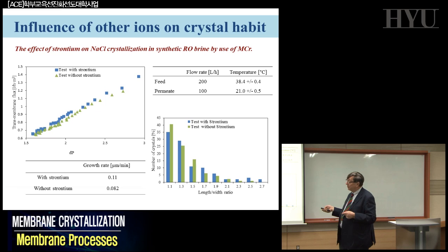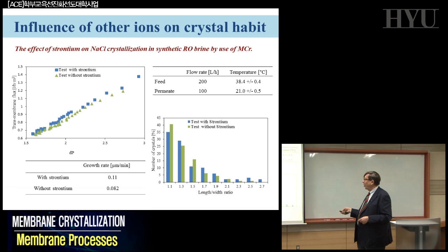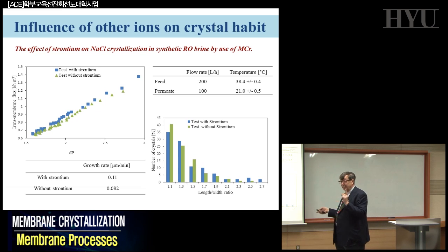But in our case, it's becoming a problem, because there is a different behavior in terms of the transmembrane flux when you have strontium present or you don't have strontium. And it's not huge, but it is present. More than this, you have some effect on the quality of your crystals. We are talking about making crystallization in a very well-controlled environment with very nice final products. However, if you have some strontium present, the number of crystals with a certain geometry, with a certain length and with a certain ratio changes significantly. So you have to check the quality. This is not a big trouble, because you know what is happening, but you cannot have exactly the same kind of crystal that we were showing before when you don't have it.